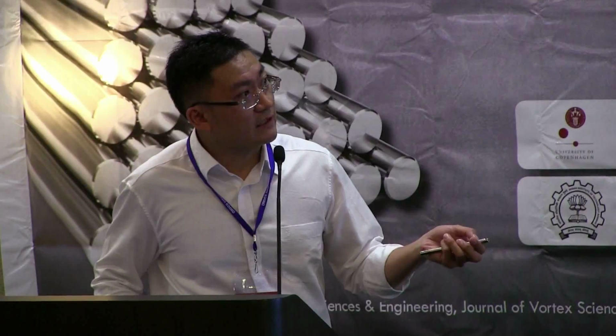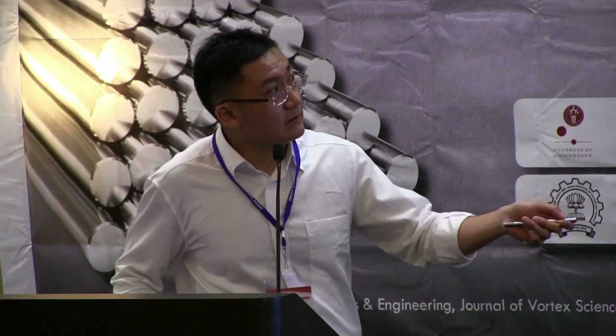And from the XPS, we can see that, for example, this is the graphene oxide. You have some oxidation groups here, but after reduction, we can see the oxidation peak, for example, this peak is much smaller, so we can claim that this is reduced graphene oxide. And this is very typical. We have the platinum and palladium different valence states. And this is the performance.